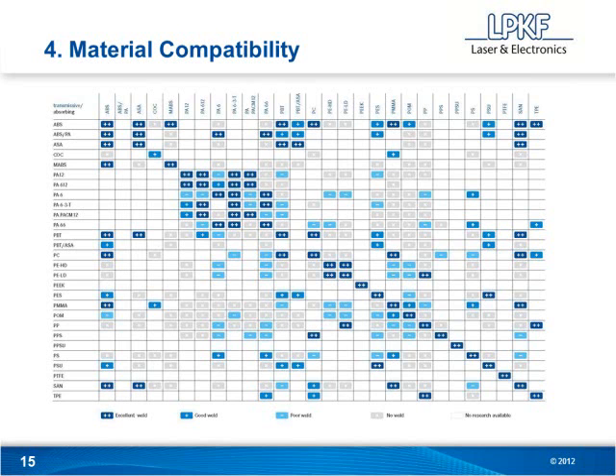Can I comment briefly? Yeah, absolutely, Tony. What we have found is that sometimes you can bend these rules a little bit because you have the volumetric absorption, because you can create more mixing than you can with through transmission laser welding. We have found that although your rules are generally very true, in some instances we can tweak those rules just a little bit because of the enhanced degree of mixing. It's not always possible, but in some special circumstances it might be.